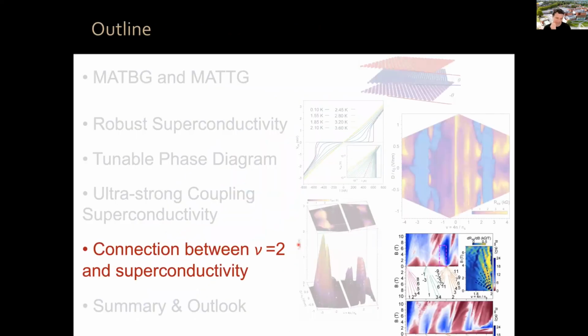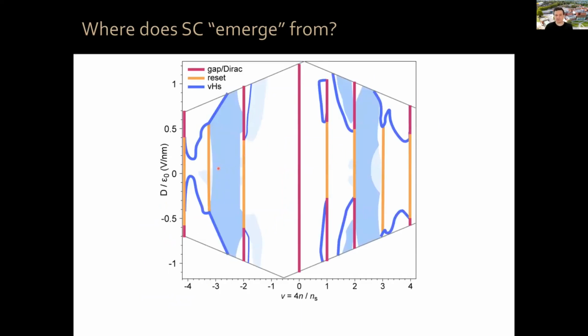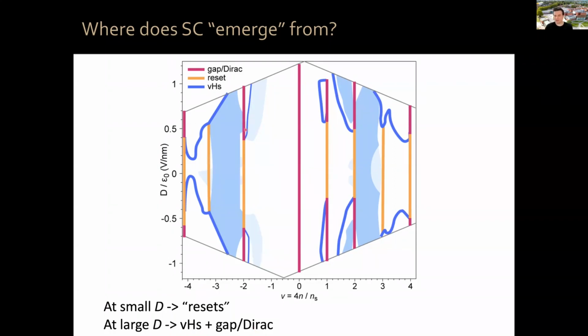Okay, let me just take a couple of minutes to tell you about the deep connection between nu equals 2 and superconductivity. So where does superconductivity emerge from in this system? As you saw, the superconductivity at small displacement fields is bounded by these two resets, mostly, okay, between 2 and 3. And then at large displacement field, something extra can happen, okay? So it's bounded by Van Hove singularities plus gapped Dirac regions, okay? At large displacement field, resets at small displacement fields. It turns out that through analyzing this data, we have realized that the superconductivity arises upon doping the nu equals 2 in absolute value, so -2 or +2, broken flavor symmetry ground state, okay? What does that mean? Okay?